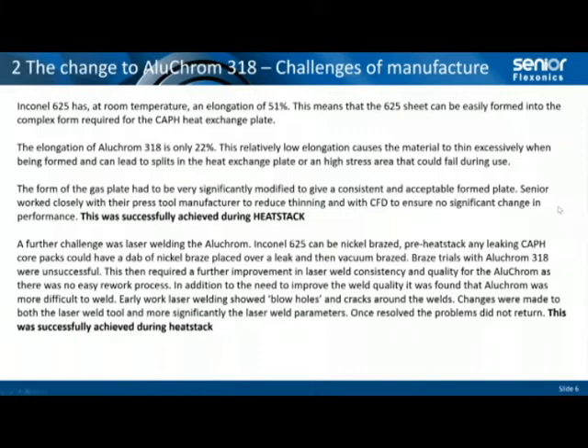But with working with AluChrom at this stage, we were able to achieve a cathode air preheater with the same performance as the 625 formed cathode air preheater, but with a very much changed profile. The other problem we found with AluChrome almost straight away was with the 625, we could nickel braze it, which meant that when we were laser welding, if we had a small leak, we could put a dab of nickel braze over the leak, vacuum braze it and repair it.